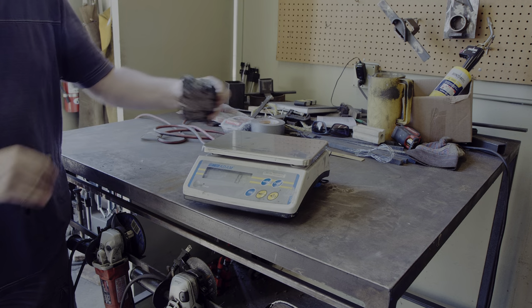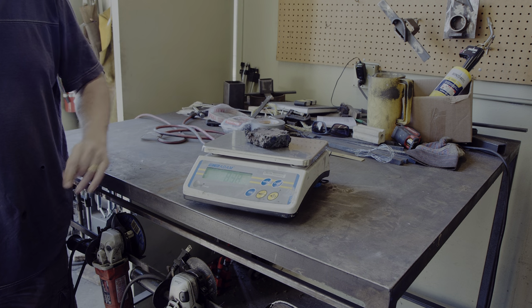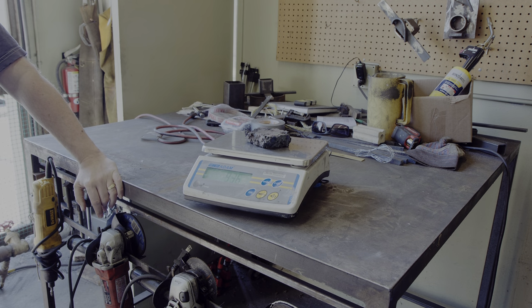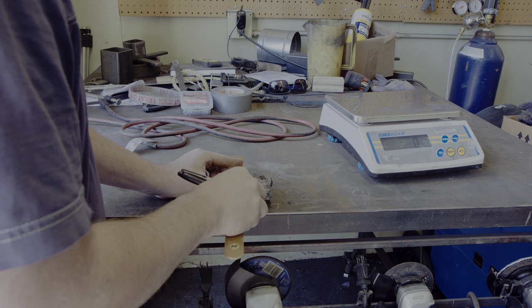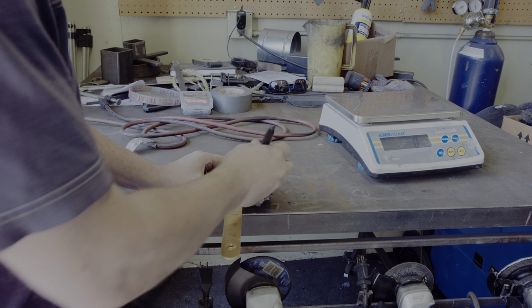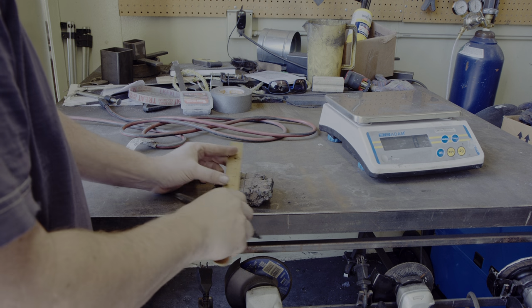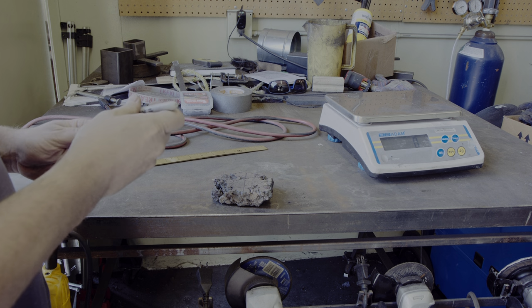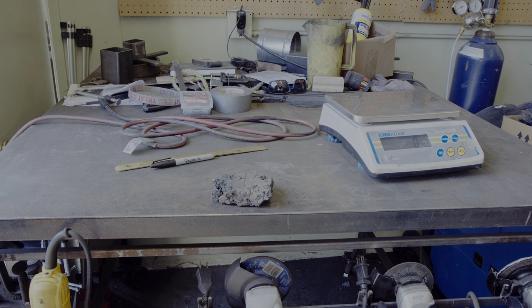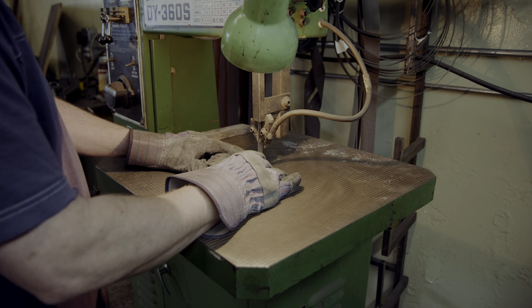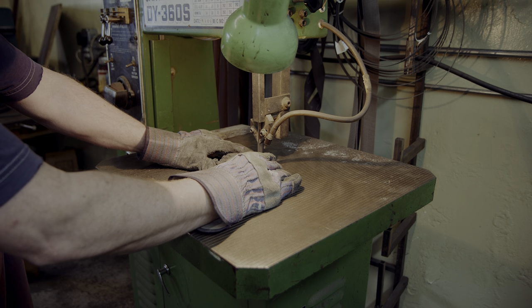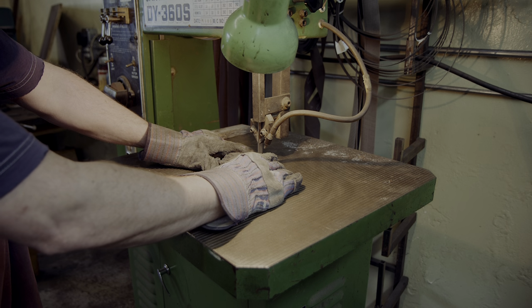It is surprising that even though we only put in roughly 10,050 gram, that we did not lose more material. What I am showing now is some of the steps of folding and forge welding the pack until it turns into usable material. This is surprisingly time intensive and also a little bit error prone, as the material is quite dirty and I need to be able to remove all inclusions.